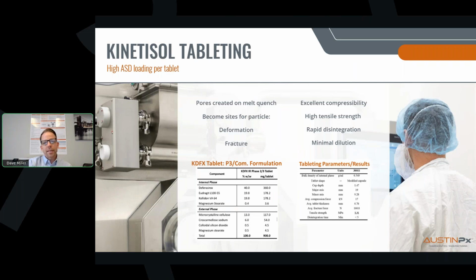So the result is good tablet tensile strength with rapid disintegration and minimal excipient dilution in the addition of tableting excipient. So we can often achieve very high ASD loadings per tablet, 75% or higher. That obviously translates to less excipients in the final product and reduced pill burden. And in many instances, we have examples where we've reduced a multi-tablet approach to a single tablet solution in converting from spray drying or HME to KinetiSol.